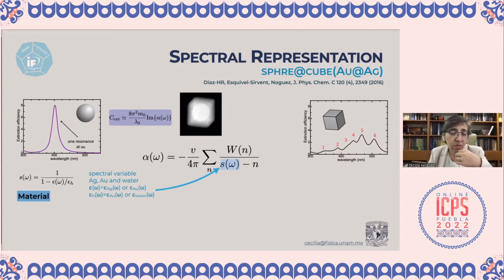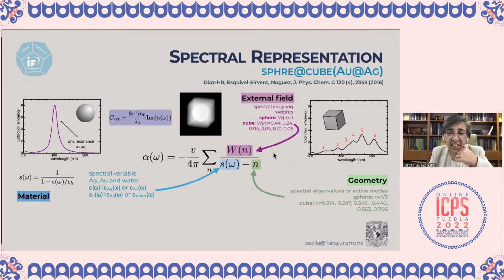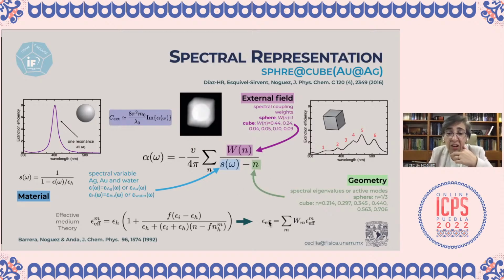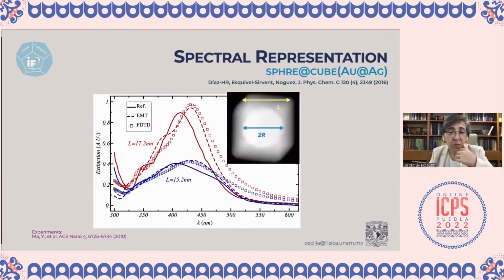And now, using this concept of the spectral representation, we can arrive, by a theory that we developed, and in this paper that is here, we can separate these contributions from the matter, let's say the dielectric functions, and the geometry, and we can know how much of these modes are coupling with the external field. Okay, and at the end we can finish with an effective response of the nanoparticle, and we can compare with experiments. So now you can, in some way, design the response of these nanoparticles, comparing with experiments and other kinds of methods.